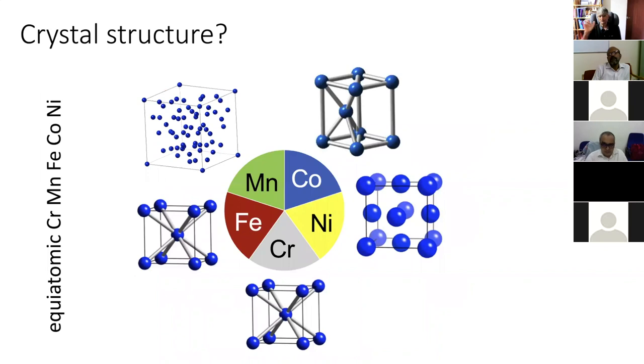We then need to think about what is the crystal structure that we should expect from mixing these elements together? Because ideally we want a nice cubic crystal structure, preferably the FCC form, whereas the constituents of your high entropy alloy will have many different structures. So for example, iron is body-centered cubic at room temperature, chromium is also body-centered cubic, nickel is face-centered cubic, cobalt is hexagonal, and manganese has a unit cell with some 58 atoms in it, so it's a more complicated structure. But nevertheless, when you make a high entropy alloy with equiatomic amounts of all of these elements, it ends up as FCC, which is something to think about.